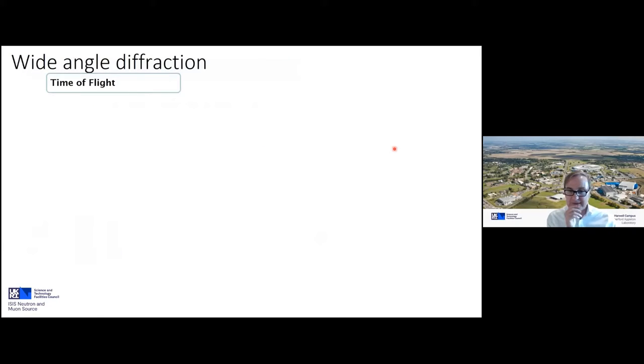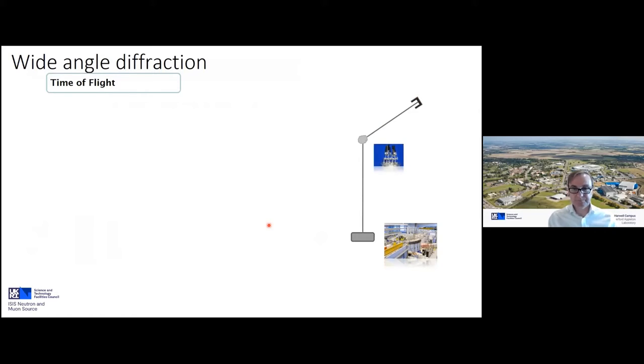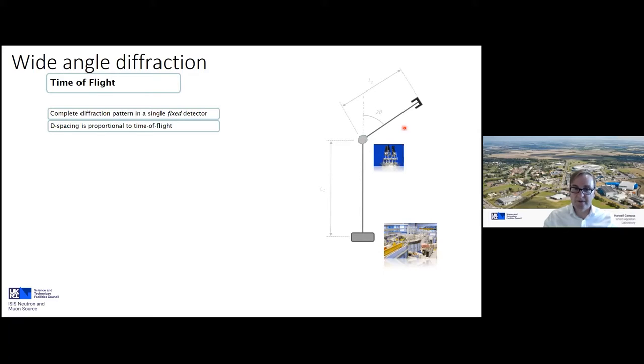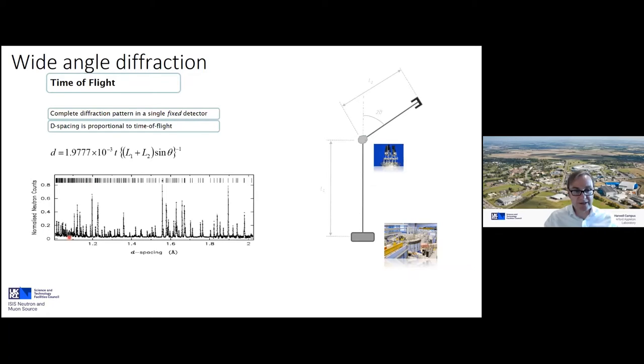So what does that mean for an experiment? Let's just take one example. In this case it is diffraction. So we're going to have our moderator or our source of neutrons. We're going to have a sample and we're going to just have a single detector at some distance and at some angle. Okay, so we put a sample in. And the key feature here of the neutron technique is that within a single detector, we measure the entire diffraction pattern. Because basically the d-spacing in your crystal is going to be proportional to the time of flight. So if you know the distance between the moderator and the sample and the detector, you know the scattering angle, then you can basically measure an entire spectrum. It's a very simple expression. You can see within a single detector, we measure this entire spectrum.